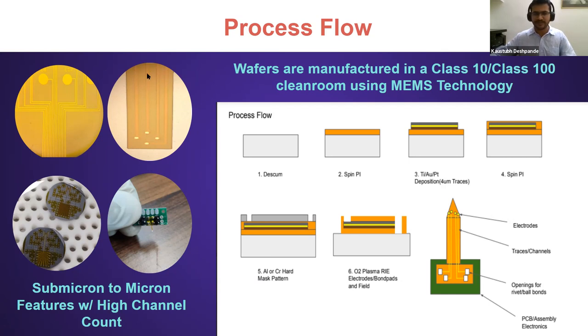So these are platinum electrodes with thin film titanium, platinum, gold traces. So you're not just able to harness the benefits of using precious metals, but with this, you're also able to drop the cost significantly because you're not using a lot of metal. Finally, these devices are then released off the silicon wafer in IPA or in Microposit, and then they're assembled onto PCBs to connect to amplifiers and recording stations.